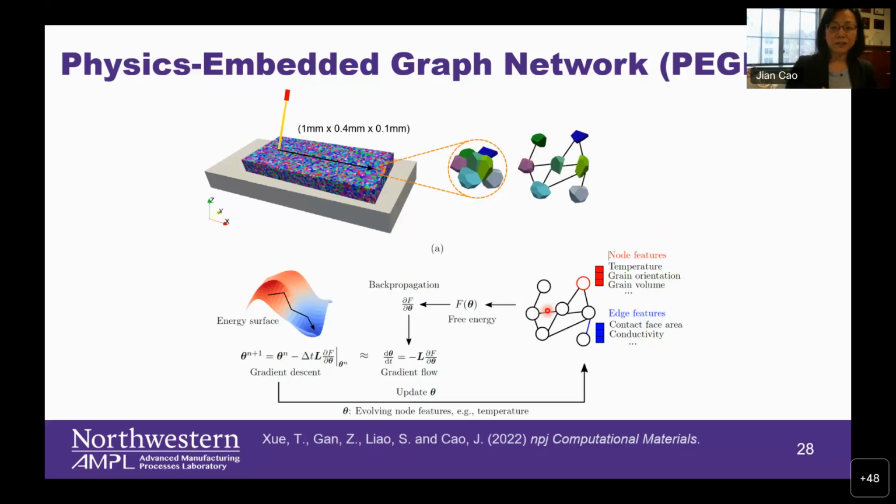So for the edge, we are actually solving the Allen-Cahn equations to look at how that will calculate the liquid-solid fractions and also control the grain growth. So that's the physics calculated around the edge. But what it does is build up the graph network to do this calculation, so it's kind of a reduced order modeling approach. And then you calculate the free energy and minimize that.